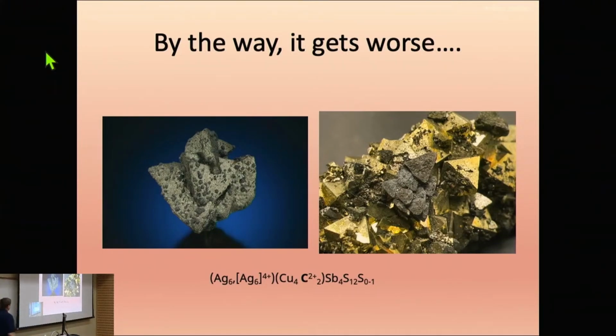Look at the structure though. The structure separates out everything. We've got a silver, 6 of these, and some more silver, 6, but with a different valence because it's unbalanced. And we have to stack that with copper and something else. That something else can be iron, it can be cadmium, it can be zinc. Then we have to balance the antimony along with some sulfur, leaving one hole that's left.